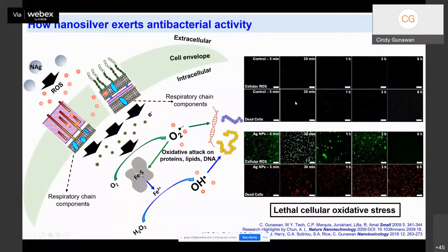And as a result, or in agreement, we only detect a low amount of dead cells in the control, shown here by the red cells. So what happens if this bacterial population is exposed to silver nanoparticles? As you can see here, the exposure of the bacteria to the nanoparticles leads to the rapid generation of lethal levels of cellular oxidative stress, as you can see here with the green cells. Even after only 5 minutes of exposure, we could detect high levels of cellular ROS in the cells. And consequently, we also observe high levels of dead cells.